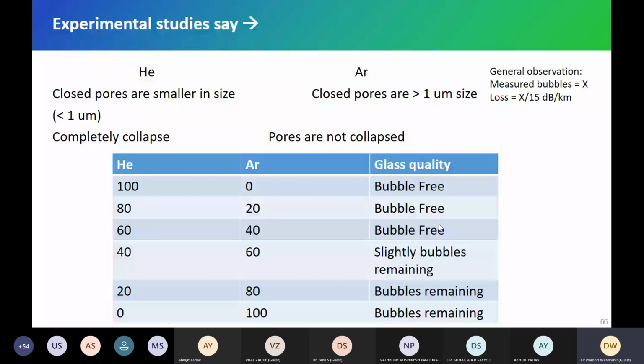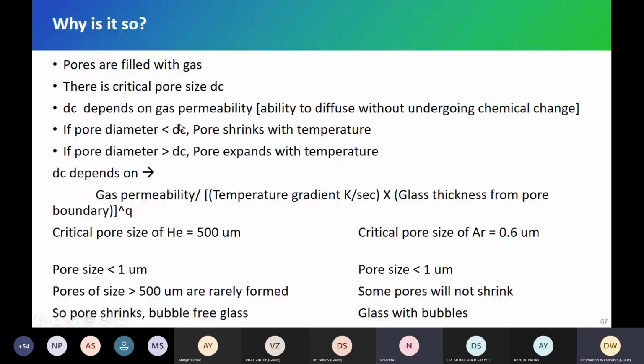So why is it so? The reason is that generally our pores are smaller in size, right? Generally 1 micron size. The pores that we saw are 1 micron or less than that. Some are 2 microns, some are 10. So there are different sizes of pores. Now, with helium, there is what is called a critical diameter, a critical pore size. If your pore diameter is less than critical, then it shrinks. If your pore diameter is more than critical, then instead of shrinking, it expands.